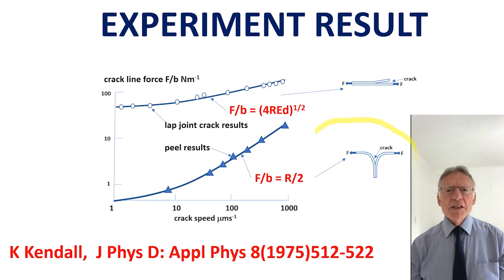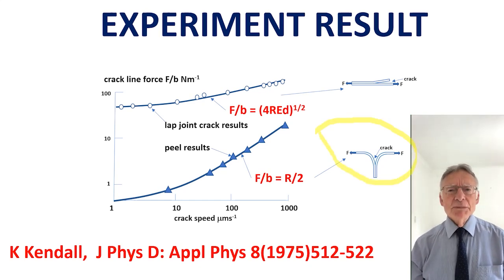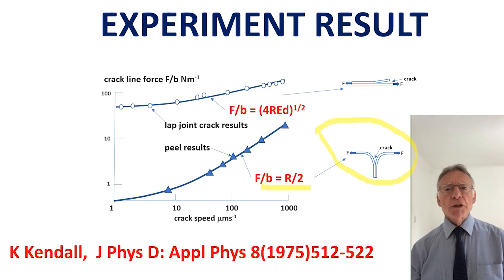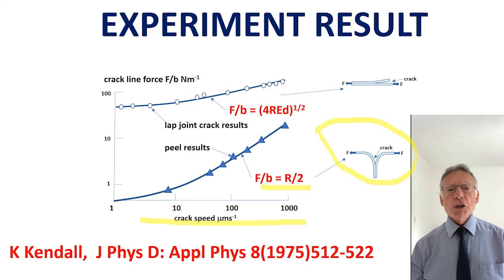Experimentally, I tested this equation with rubber strips by doing a simple peel test to measure the work of fracture. I call this R here because it's not really equilibrium. So it's different from W, the equilibrium fracture energy. Naturally, this must depend strongly on crack speed, so you must control crack speed to get the right answers. Then I plugged the value for fracture energy into the lap equation to compare with the results on lap joints, and it fitted. Because elastic modulus is a big number, it enters the equation, so force increases by a factor of 100 over simple peeling.